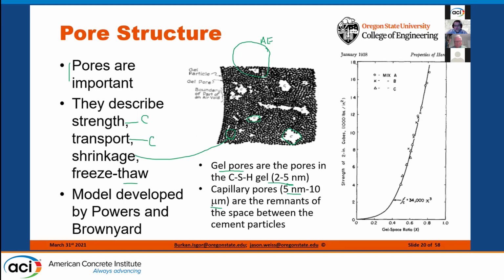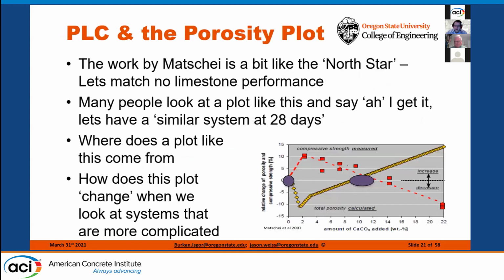And almost 80 years ago, Powers and Brownyard developed a model that is really the basis for a lot of what we see in the code. It's a lot of the basis for really how cement developed and how cement properties are explained. And in fact, if you plot porosity, and this is a gel to space ratio, it's a form of porosity that Powers used, it can be directly related to things like strength, like transport properties, like shrinkage when we use the correct models.